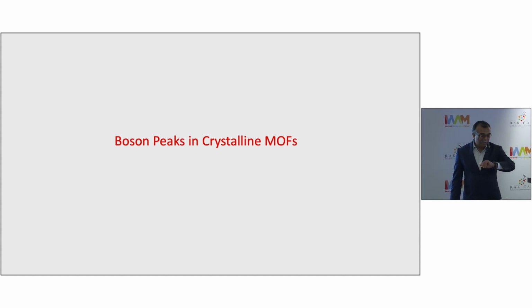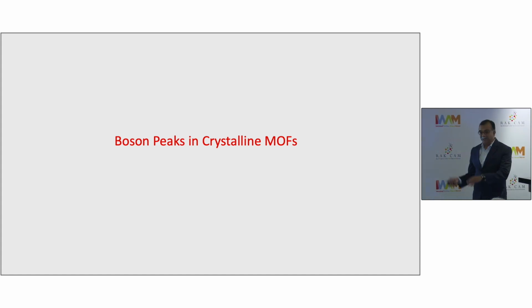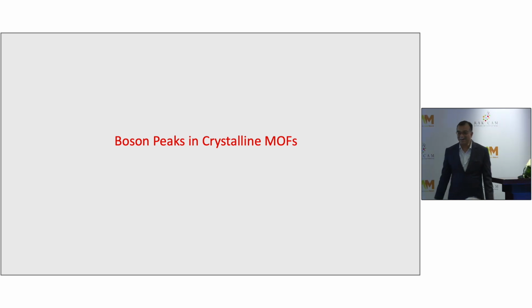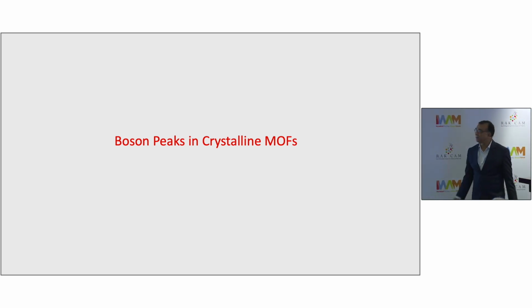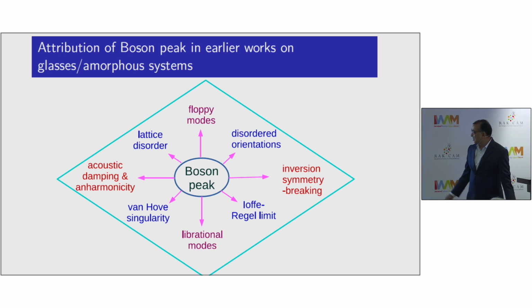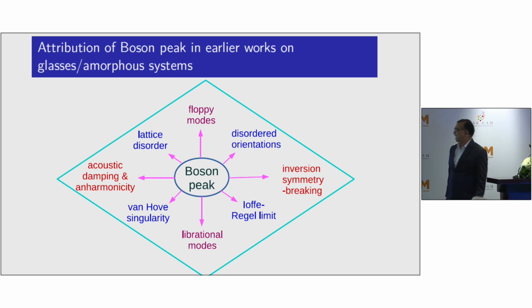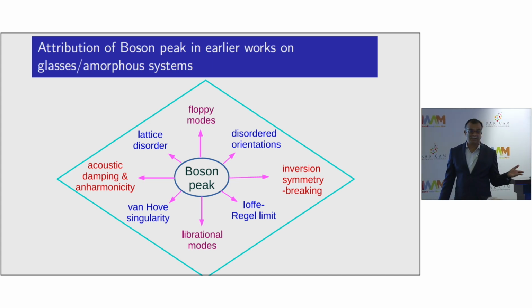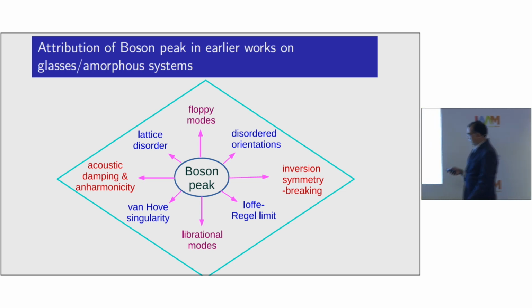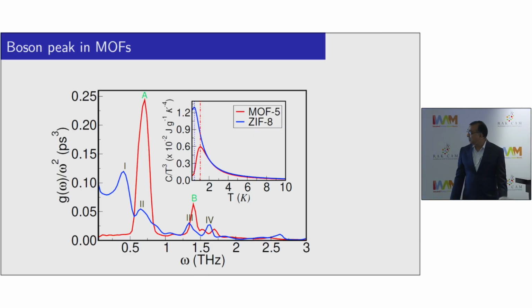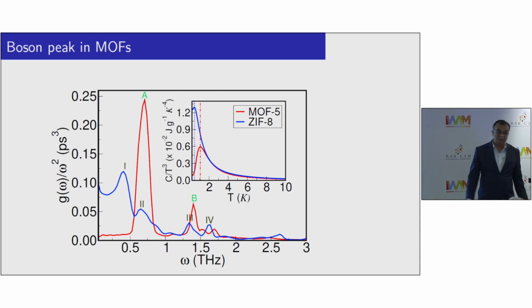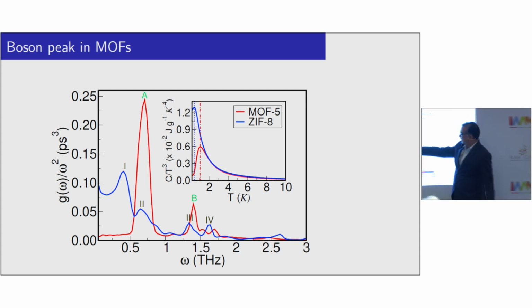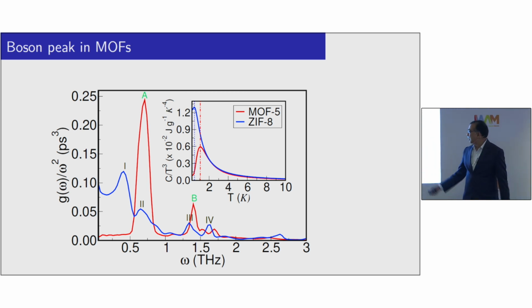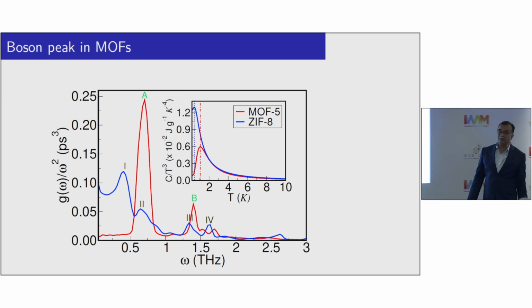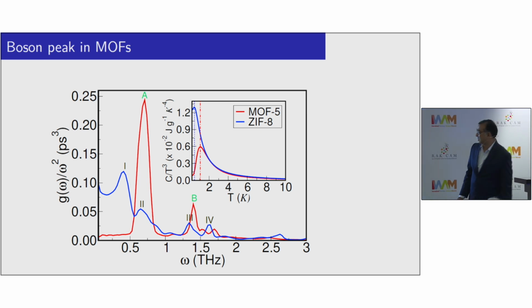Okay, I'll very quickly go through the last bit, which is about the boson peak, which relates to both flexibility and amorphization ability of MOFs. Basically, in the past, the boson peak has been associated primarily with glassy or amorphous systems, and in some cases, it has been observed in crystalline systems as well, and the causes given are here. What we show is in MOF5 and ZIF8 both, you do see a boson peak. This is specific heat by T cubed, and it develops a beautiful sharp peak at very low temperatures. Very unexpected of a crystalline system.